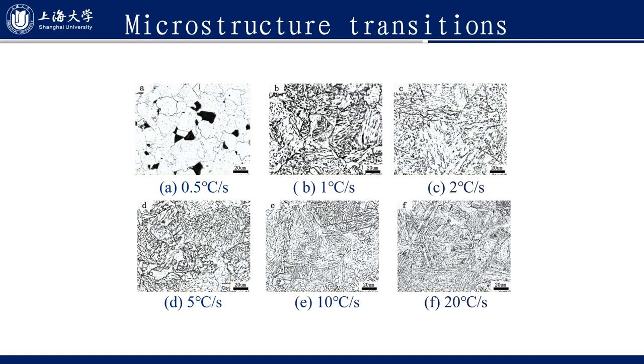So the microstructures for the steel are: for 0.5 degrees per second, ferrite and pearlite. For 1 degree per second to 10 degrees per second, granular bainite. For a cooling rate larger than 10 degrees per second, a mixture of bainite and martensite.